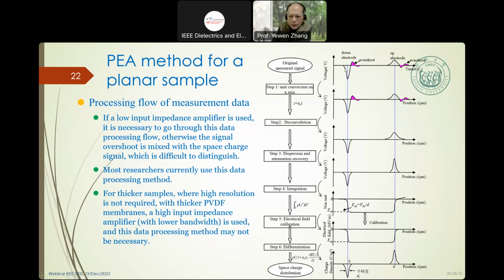So for this one, first we get the original one, then change the x axis from time to position. Then we get the data deconvolution. We get this clear one. Then this one is deformed, so we need the transducer's dispersion and attenuation curve. So we can get a similar one. Then we integrate this one, so we get the field. Then after calibration, we can get the electrical field. The last step, we differentiate this one, and we can get the space charge distribution.